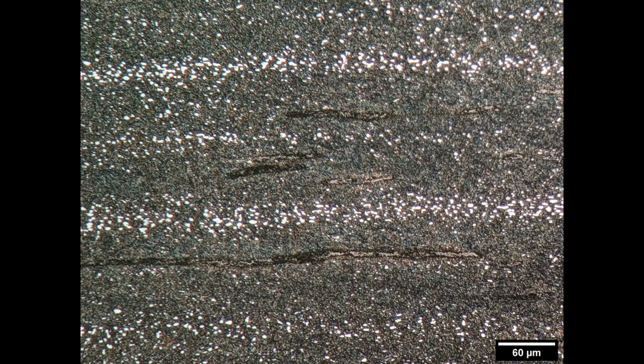Looking at the microstructure at a little bit of a low magnification, we can see clear carbide bands. This is what gives us the pattern. This is what gives Wootz its unique properties. So we got great banding in this material. So Spencer's doing a great job of mimicking the microstructure of Wootz. You can also see some gray elongated features in the steel, which are the impurities, also called inclusions. This steel has a relatively high content of them.